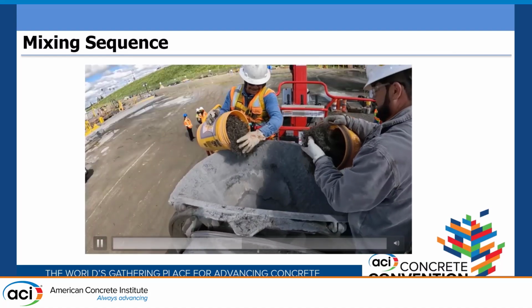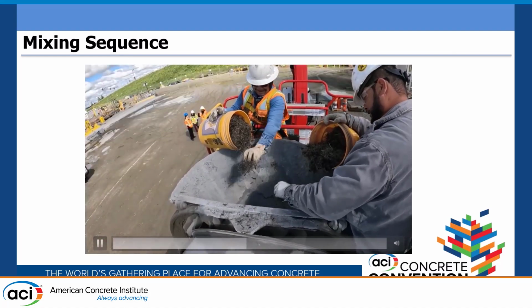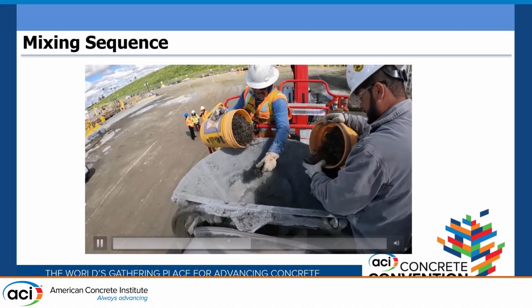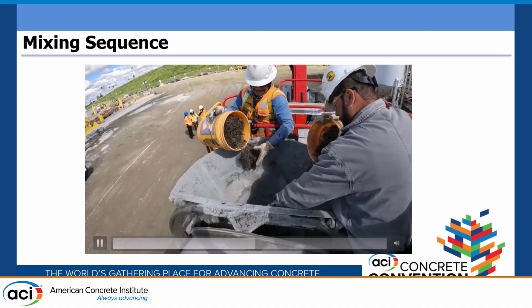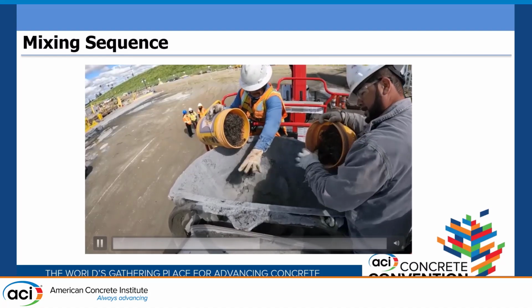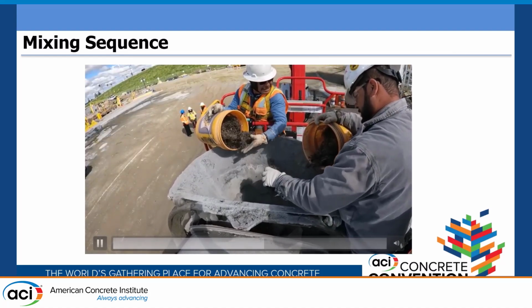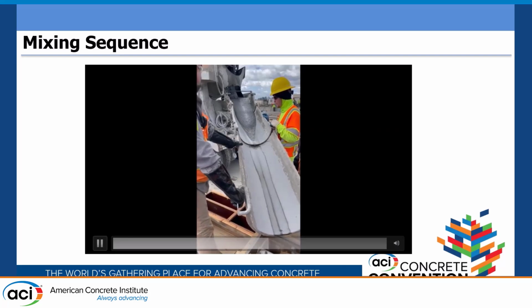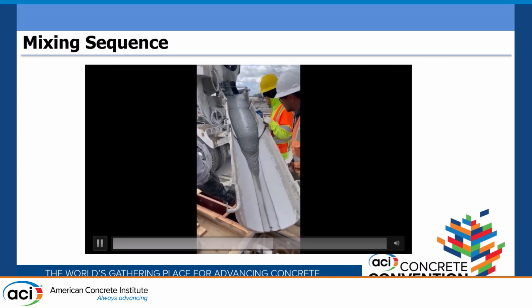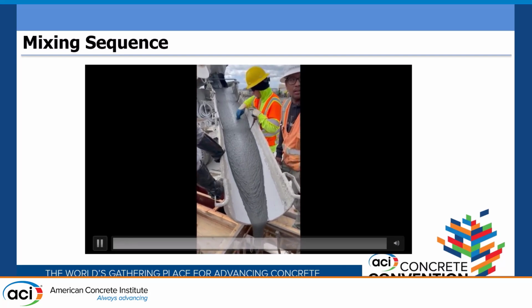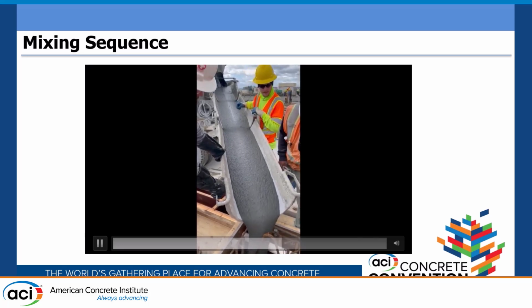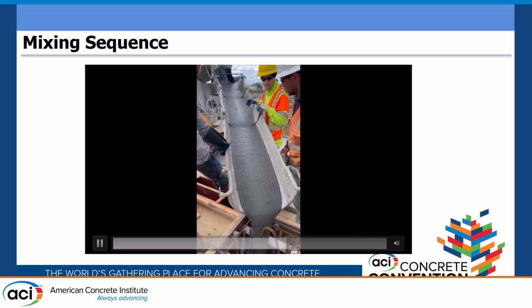But this is the part where we put in the recycled fiber. You see how fluffy they are. We have to manually disperse it. It takes around 15 minutes, because we're too slow, since we're just putting in the fiber. So this is what went out in the UHPC truck for the manufactured fibers.